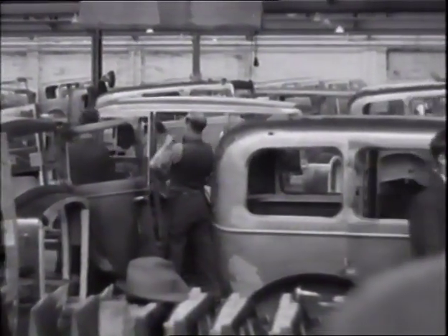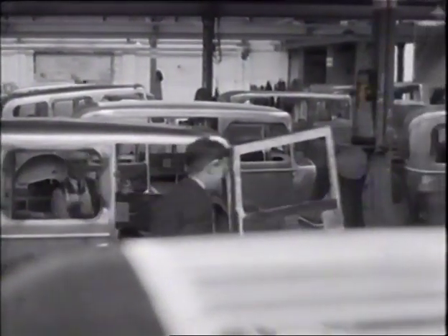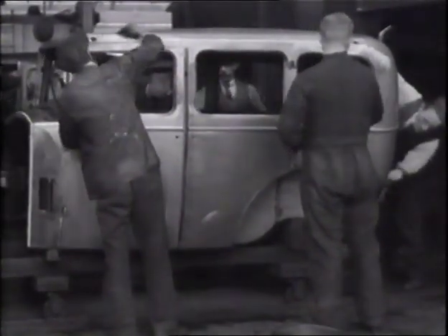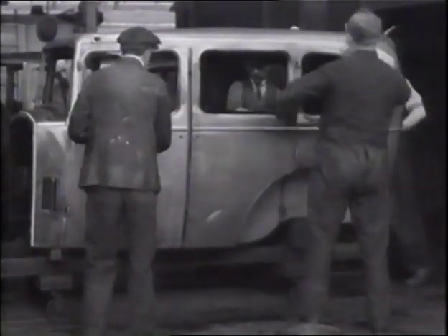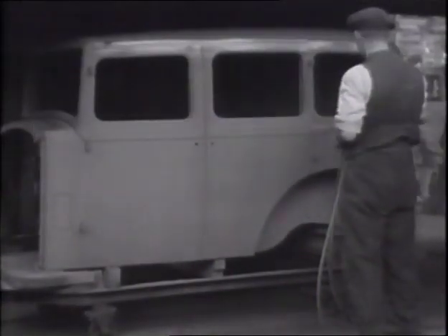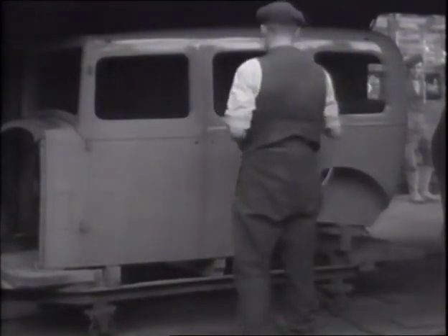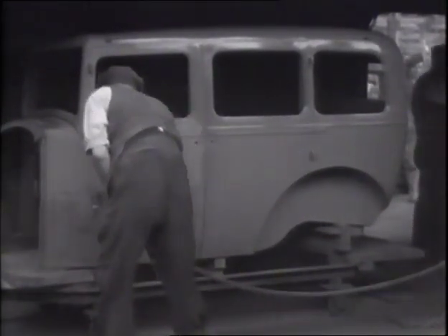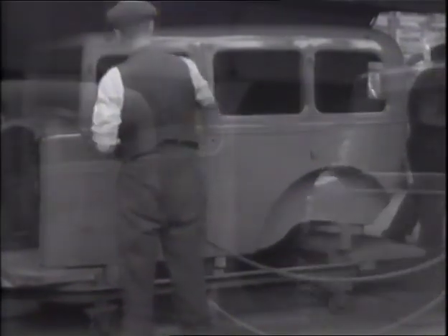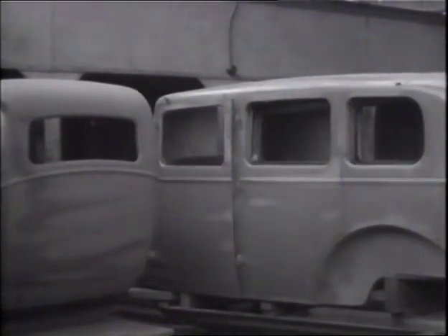When all the steel panels are on the wood framework and the doors have been hung, the panels are carefully and thoroughly cleaned, and after that they receive their first coating of cellulose, which is known as the undercoat or primer. This is put on, as are all the other coats, by a rapidly operating spray pistol, which gives a beautifully even distribution. Immediately it has been painted, the body is pushed into a huge high-temperature drying tunnel, and it stays in this tunnel for some 9 hours or so, emerging from the other end to receive yet another coat of primer.